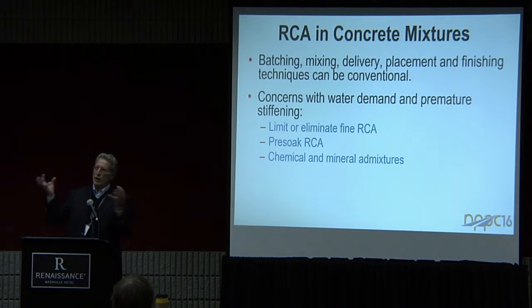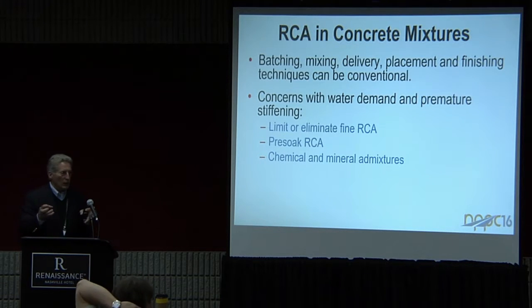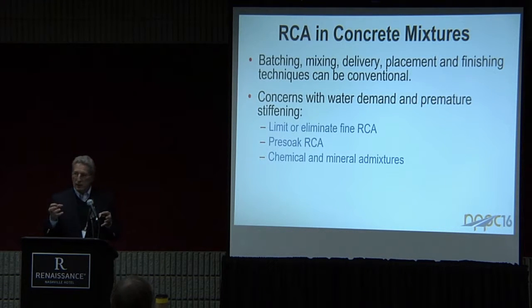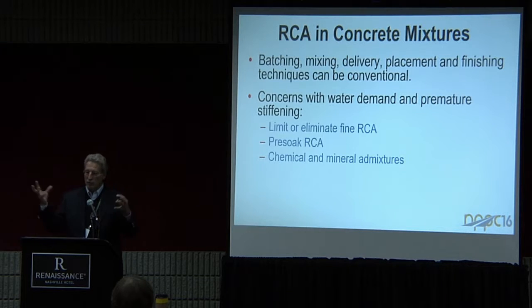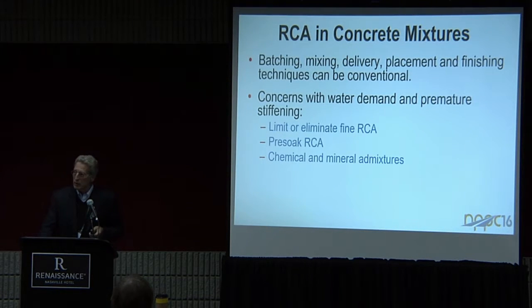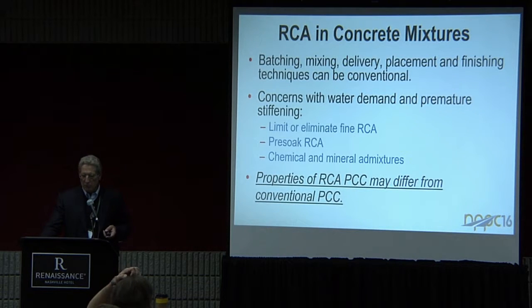Pre-soaking it so you don't draw a lot of water out. Again, the crushed concrete is a relatively absorptive material, with a little higher absorption capacity than conventional aggregate. It's going to suck water out of the mix, which tends to make it stiffen early. So if we pre-soak it and use the aggregate in a saturated surface dry condition, that eliminates those problems a lot of times. Chemical and mineral admixtures, obviously fly ash, water reducers, high-range water reducers, plasticizers, etc., will all help those problems as well.